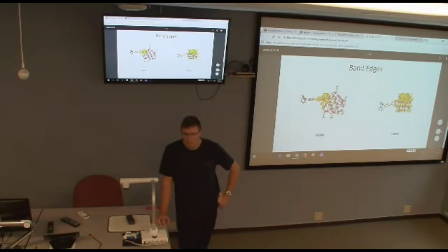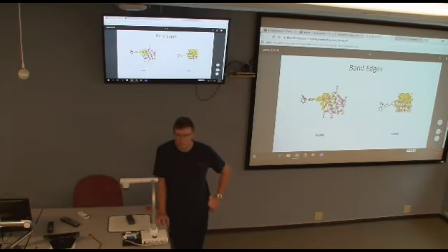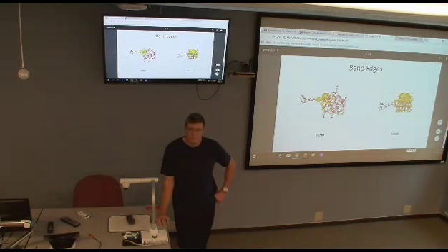you're preparing this kind of thing mainly for the dynamics, right? And in dynamics, we probably will be restricted. I hope we can do HSE, but there is a good chance that it would take too many resources, and we probably have to give up and go back to the PBE functional, right? So at least we need to understand how trustable it is. We know we are off in the energy range and so on, but if we really see this hybridized picture as you've seen with your PBE functional, then it's a good sign, and at least we can trust our VASP calculations when you apply them to the dynamics, right?